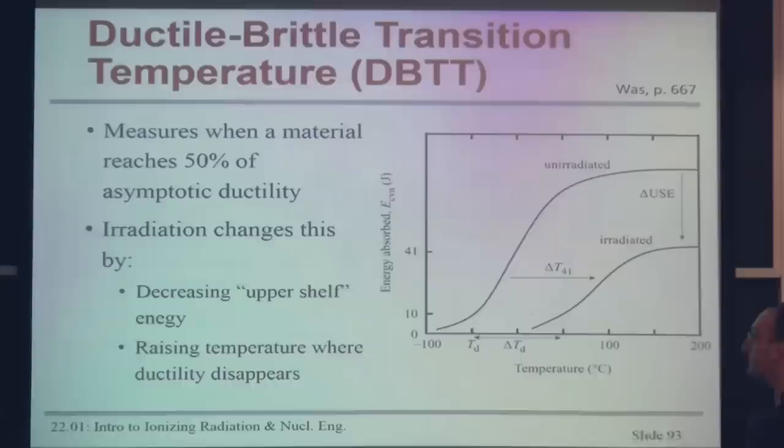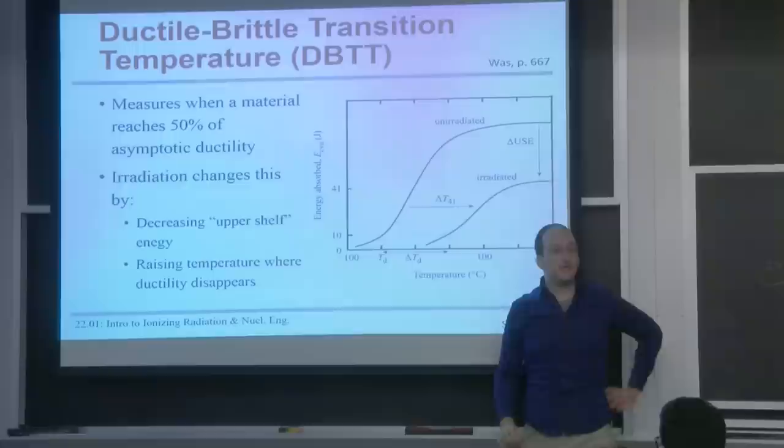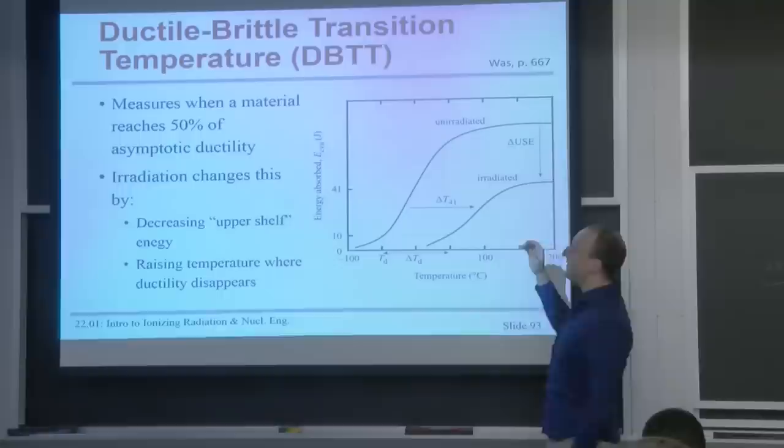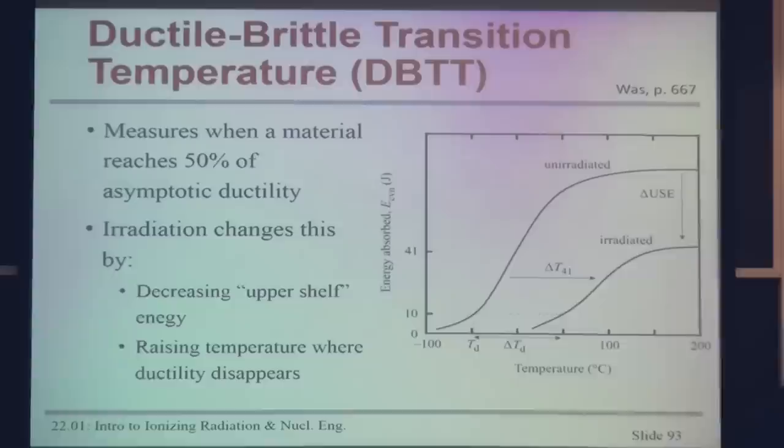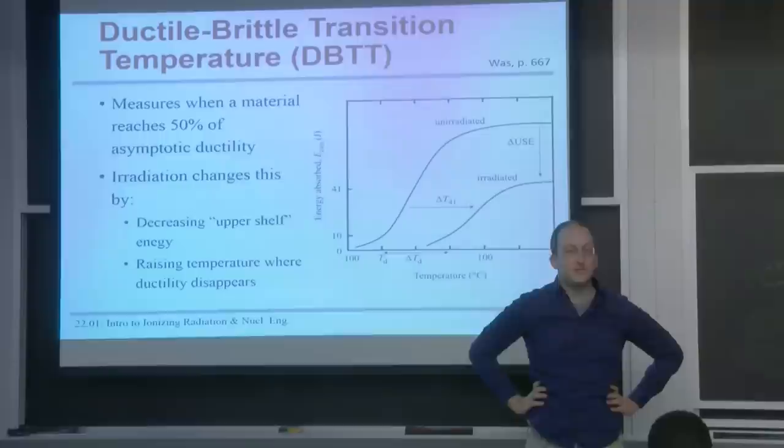To show you what something looks like when it's not brittle, the same test is done in what's called the normalized condition, where you simply heat the steel to a high temperature, relaxing out most of the defects, and bringing back as much of the perfect crystal structure as possible, which is really good for letting dislocations move through it. So the same test is done by the same awkward feller who likes to stand there and not breathe. But you'll notice a very different result of this test. Something like 18 times more energy. And you can qualitatively see the difference between these two conditions by looking at the fracture surfaces. Something that's ductile would tear more like taffy, whereas something that's brittle would cleave or break in half much more smoothly. So these are the two pieces of metal that we just showed you. The one that absorbed 180 joules by lots of deformation, and the one that absorbed 10 joules by fracture in a brittle way. This is what you want your reactor vessel to behave like.